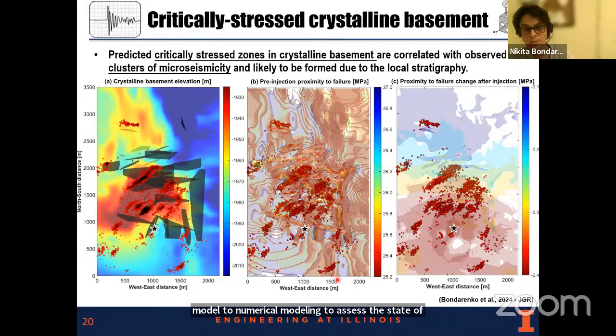Here we can see that it's non-homogeneous, obviously, on a scale of a few kilometers. At the same time, there are zones which are more critically stressed, and it partially correlates with the observed clusters of microseismicity - they have a tendency to be localized in zones which are more critically stressed before injection due to local stratigraphy.